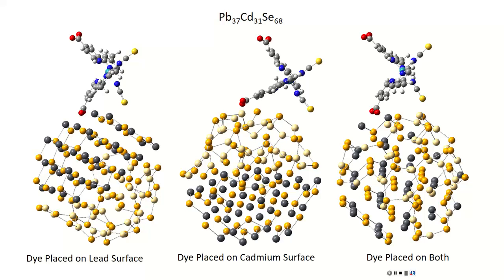In this case, I don't know about sulfur, but in the solution, it can neutralize that charge or the attractions between the surface and carboxylate. If you involve solvents, your attachment will be different. You will have a completely different story, because you will screen out this very strong dielectric effect, and your charge will not be as strong anymore, especially with a large dielectric constant.